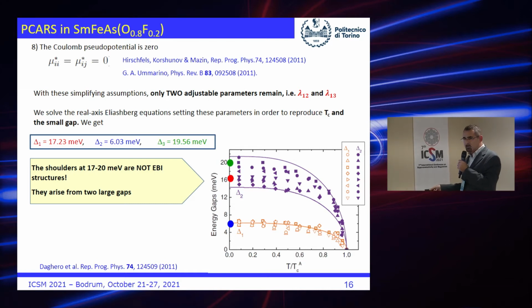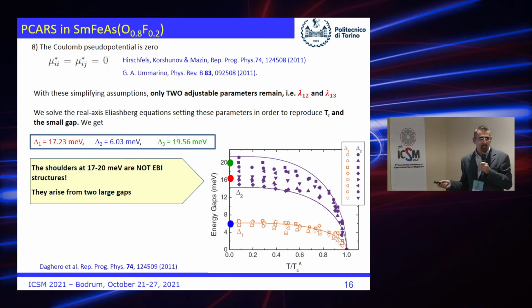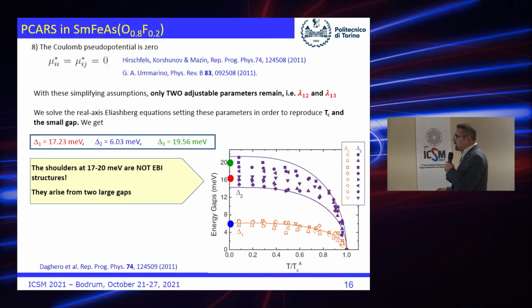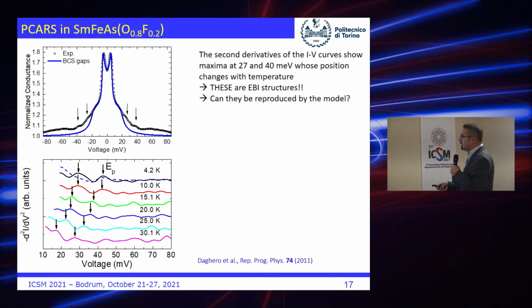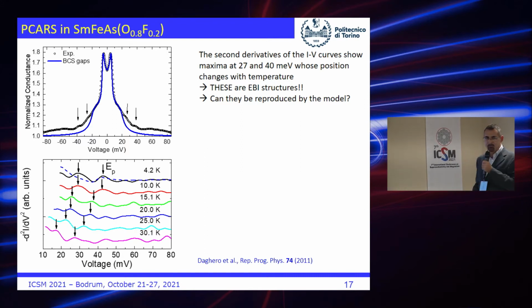And it turns out that the other two gaps are here. So these are not electron-boson interaction structures. These are really the two gaps. We see only one because it is difficult to distinguish, but there are two. And now, are there electron-boson interaction structures in these curves or not? Yes. These are the electron-boson interaction structures at higher energy, so about 27 and 40 millielectron volt. Indeed, if you take this curve, the black curve, which is the experimental data, and you calculate the second derivative, actually the derivative of this, you change the sign, you obtain this curve here. And at different temperatures, you see that this has peaks that move in energy.